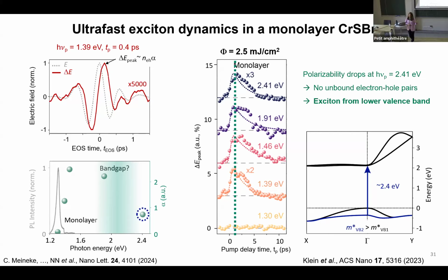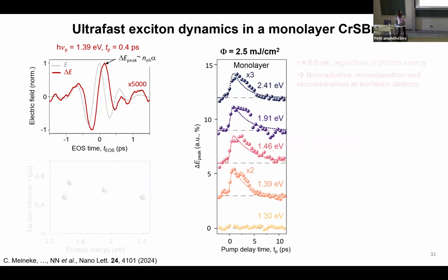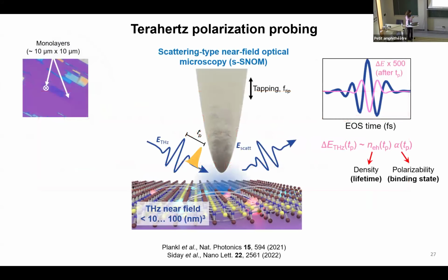But during the acquisition, there is way more information that is naturally obtained. For instance, already the amplitude of the response gives a hint about what can be the band gap or why this is happening. And so this data is for which type of measurement? This is a pump-induced ultrafast SNOM measurement. So what we do is that we pump. The entire idea when we want to study excitons in a semiconductor is to generate them. The way we generate them is to use a pump, which is a near-infrared radiation, and then the probe is a low-energy source. In SNOM, actually, we pump the excitons to generate them, right?